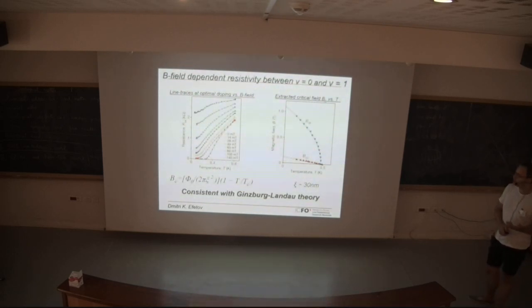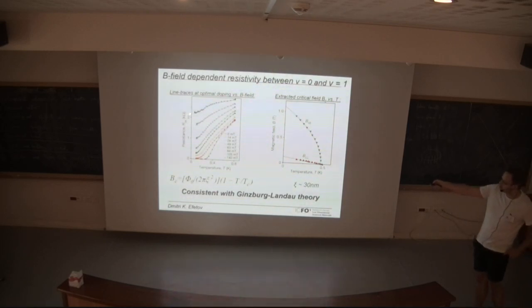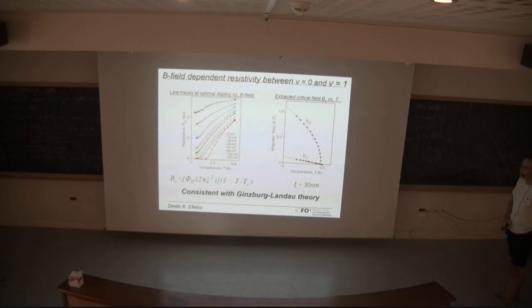Then, of course, the other thing one can do is apply a perpendicular magnetic field and see whether this superconducting state disappears. And indeed, this is resistance as a function of temperature for different magnetic fields, and as you can see, at 0 field resistance goes to 0, but at a perpendicular field on the order of 100 millitesla, this superconducting state disappears, and metallic temperature dependence is recovered.